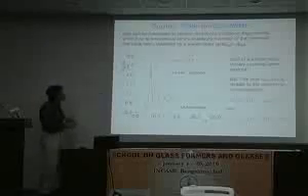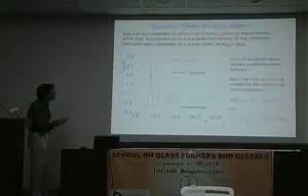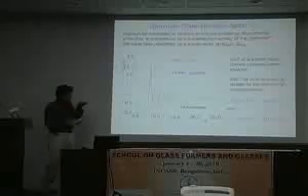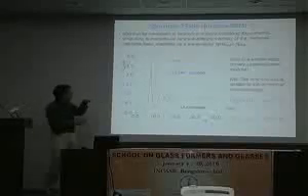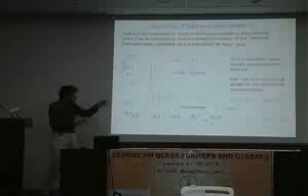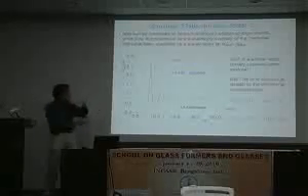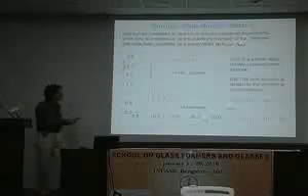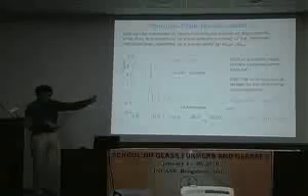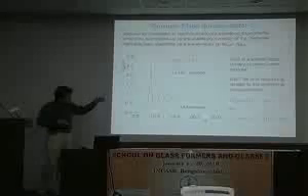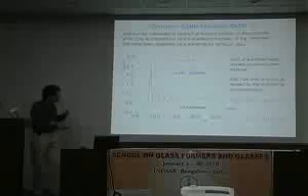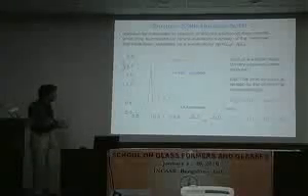Now, how does this function look? You can measure it in neutron or X-ray scattering experiments. What's happening is that you come in, let's say, with neutrons that have a certain wave vector, since they have a certain energy, and they scatter off of the sample. They come out with another wave vector. You take the difference of these wave vectors, this is your q, and you put up the detector at the end of the beamline, and you see how the scattering signal depends on this wave vector q, and this basically, apart from certain prefactors, gives you the S(q).